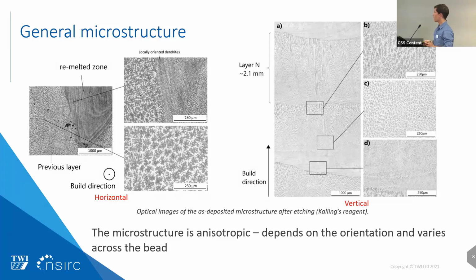You can see that we have a dual phase microstructure. The darker phase is delta ferrite, and the lighter gray phase is austenite. The microstructure is dendritic and strongly oriented. The dendrites are oriented vertically, which is also the direction of the thermal gradient during the deposition.